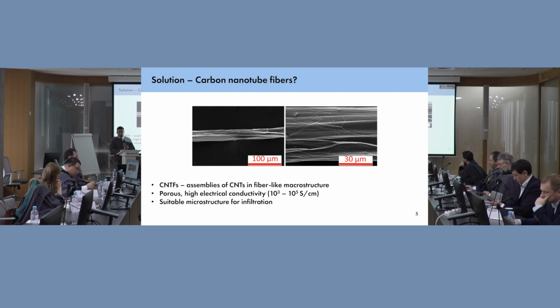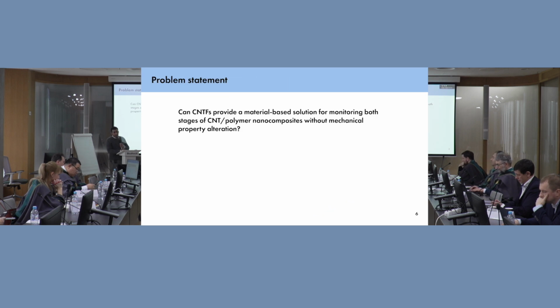We discussed in the beginning of my thesis with my supervisors, and we thought, maybe carbon nanotube fibers can give us an answer. Now, carbon nanotube fibers are assemblies of CNTs. They're assembled into a macrostructure, which is fiber-like, as you can see on the SEM images on the screen. But generally, they are porous. They have high electrical conductivity. And when it comes to polymer nanocomposites, this is a microstructure that is suitable for infiltration or interaction. And we thought, all right, let's see if we can use CNTFs to provide a material-based solution for monitoring both stages of CNT polymer nanocomposites without altering the mechanical properties.